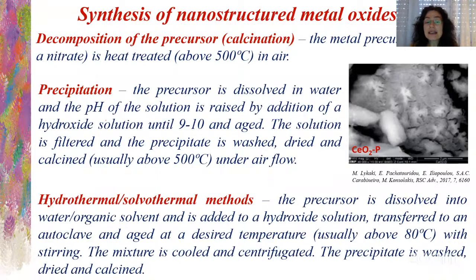There are other methods, like for example, hydrothermal or solvothermal methods, in which the precursor is dissolved into either water, if it's hydrothermal, or an organic solvent, if it's solvothermal, and is added to a hydroxide solution. So again, the basic solution. And it is transferred to an autoclave at the desired temperature, usually above 80 degrees, and it's stirred. And the mixture is cooled and centrifuged, then again it precipitates, then the precipitate is washed, dried, and calcined.